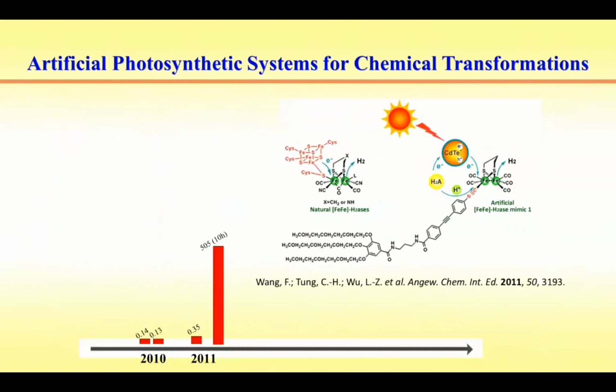With this in mind, we introduced an isocyanide ligand to anchor three hydrophilic acetates to the active site of hydrogenase mimics in order to enhance the solubility of the catalyst in water, and we use a quantum dot to capture sunlight and ascorbic acid as a sacrificial electron donor and a proton source. Upon light irradiation, more than 500 equivalents of hydrogen are achieved for 10-hour irradiation, with a maximum turnover frequency of 50 per active site per hour. This result implies that both the catalyst and the photosensitizer are regenerated, and the whole reaction is photocatalytic in nature.